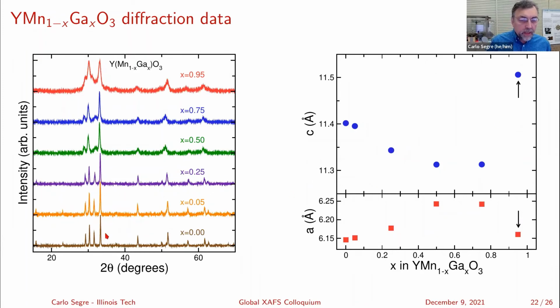And you can see that at x equals 0, of course, you get good crystallinity. And all the way up to 0.5, you can still sort of see that it's okay, but it's getting harder and harder to crystallize it well in the time that we have, so that we can anneal it. So there are real problems there. We still haven't worked it all out.